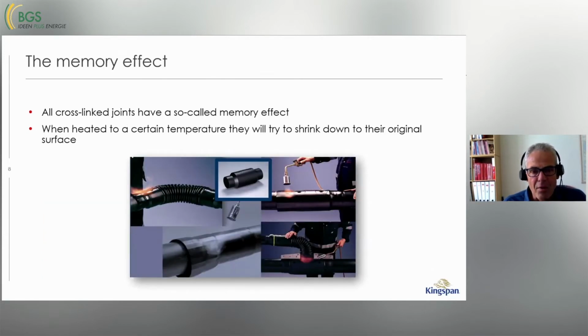The cross-linked joint has a memory effect. So when heated, the casing joint will try to shrink down to its original size. And when installed on a pre-insulated pipe, it will not be able to shrink down to the original size, because before that happens, it will meet the casing of the pre-insulated pipe. And by having the shrink force, it will put a force on the sealing that will be in between the casing joint and the pre-insulated pipe. And that is what will secure the tightness of the casing joint over the entire lifetime of more than 50 years.